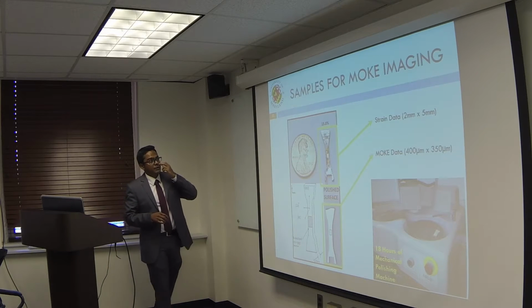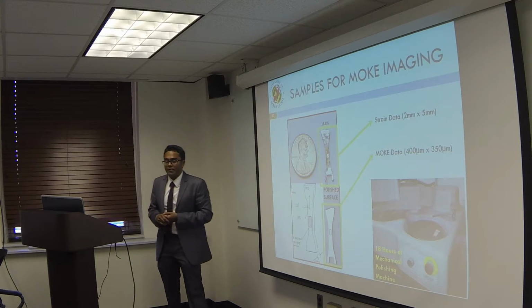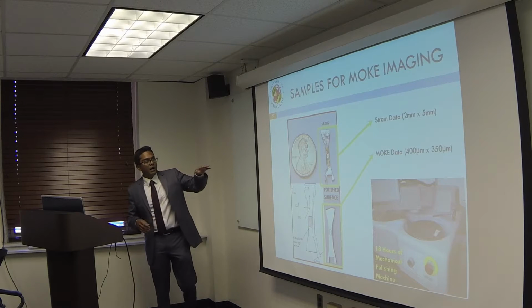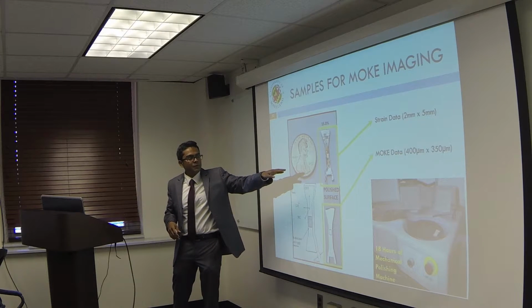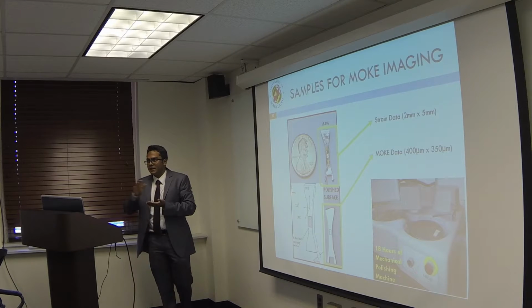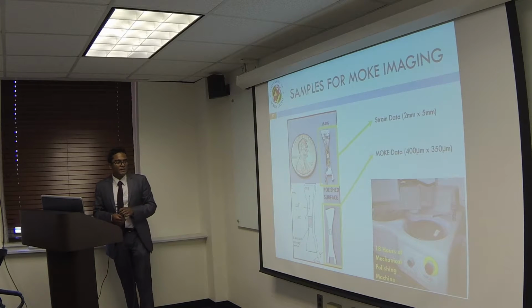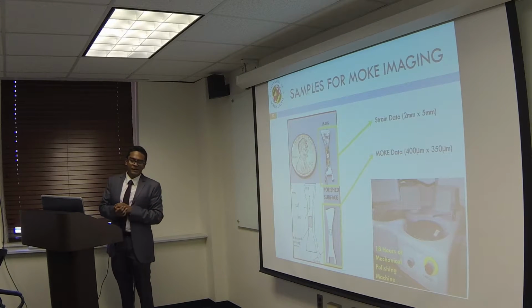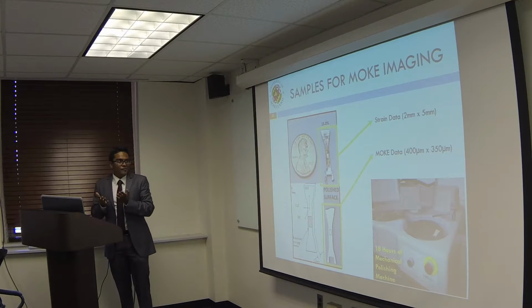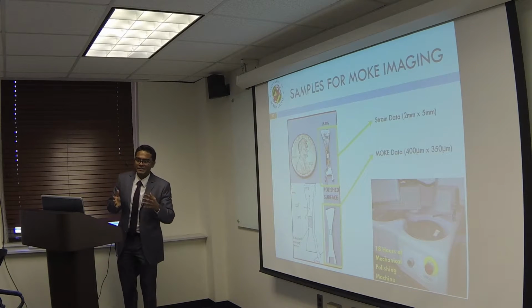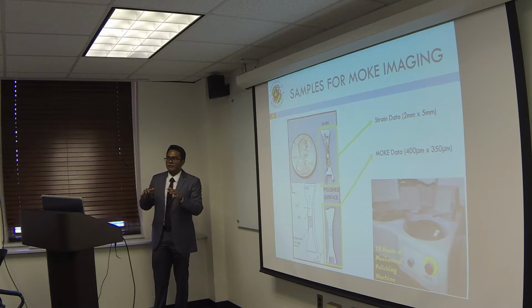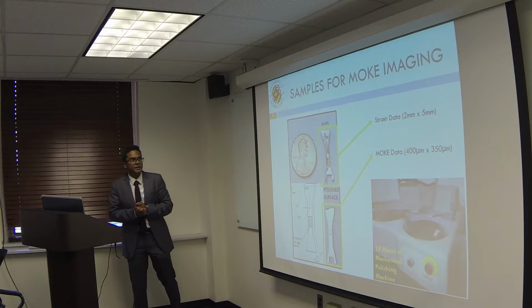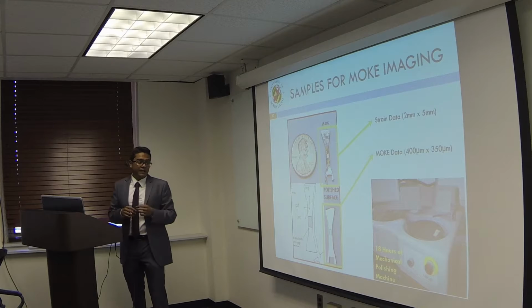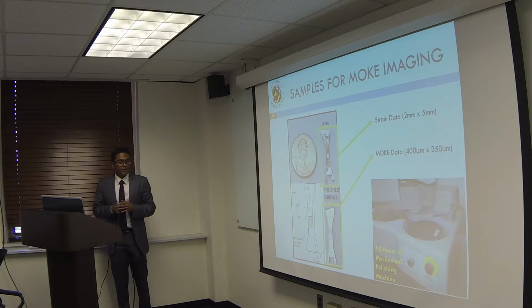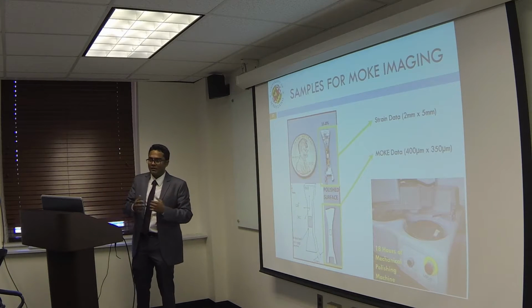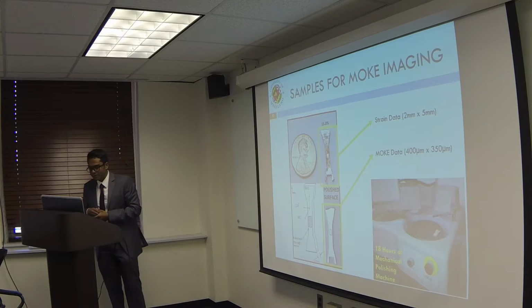So here's the sample that I used. I used the same sample that I used for my magnetostriction measurement, and I installed a bidirectional strain gauge rosette on one side, and then on the other side, I polished it. It's very hard to polish. It's very hard to attain a good surface condition, because it's very essential that we have perfect surface conditions to do MOKE imaging. So it took me about 18 hours of mechanical polishing, and finally I was able to get a sample which had good enough surface conditions for MOKE measurements.